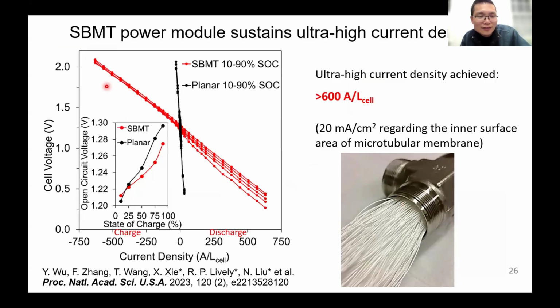So we achieved a very high volumetric current. So the volumetric current density of our microtubular cell, shown in red, is much higher than the planar configuration at the same cell voltage. Right? The red one is about 5 to 10 times higher. And this is due to the unique